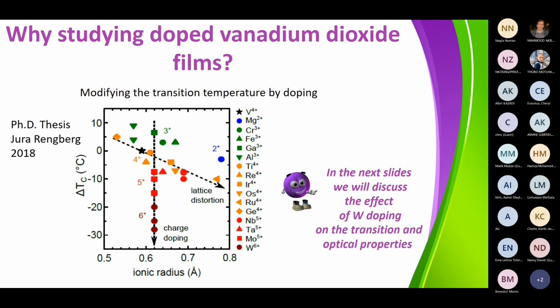Well, people have been looking at this type of materials with different doping agents. And you can see that there is a very nice PhD thesis, 2018, and they put a very nice diagram here where they have plotted the variation of transition temperature as a function of the percentage of the doping agent, as a function also of the ionic radius. So you can see that, for instance, if you are using tungsten ions, they have a very similar ionic radius as vanadium. So it means that you are going to move along a constant ionic radius line like this.